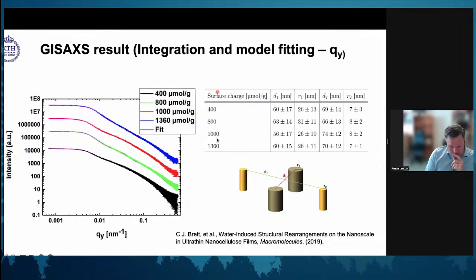And depending on surface charge, we can then determine that we have a structure that depends on... if you look at this, you can fit almost everything in the curve with two types of objects: something that has a large radius and a distance of about 60 nanometers, and something that has a small radius with about the same distance. So this model of how the structure looks is good at fitting these curves. It gives you an insight about some sort of bimodal size distribution in the films.